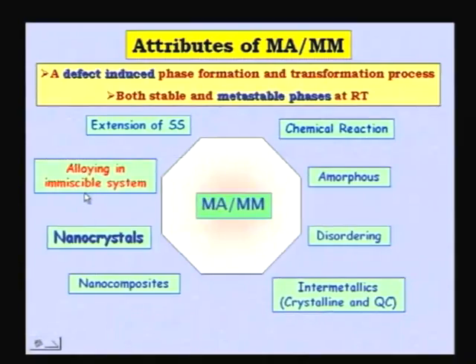This is one thing which rapid solidification processing cannot do, because in rapid solidification processing, you are starting with what? You are starting with liquid. Your starting material is liquid. If in the liquid the two elements do not dissolve, then you can't help it. So if the two elements have not dissolved in the liquid state, then you cannot have solubility of A and B in the solid state, because you are already starting with two liquids, and if you are cooling fast, those two liquids may give you two solids.